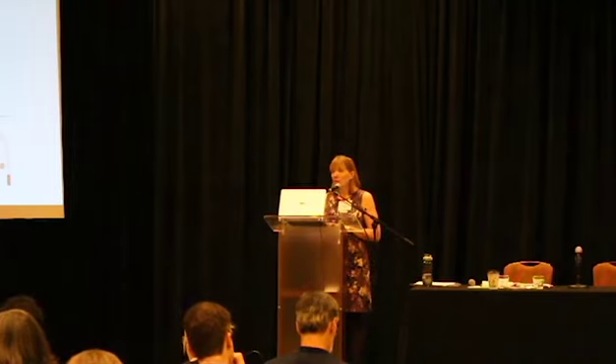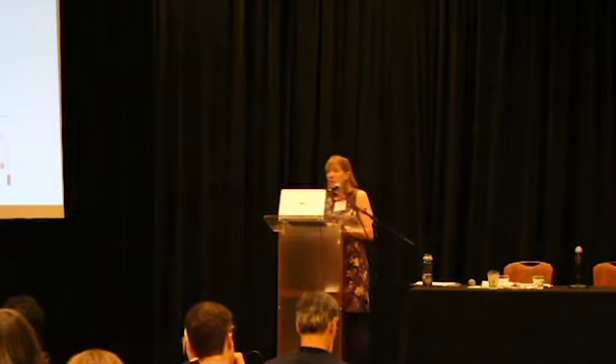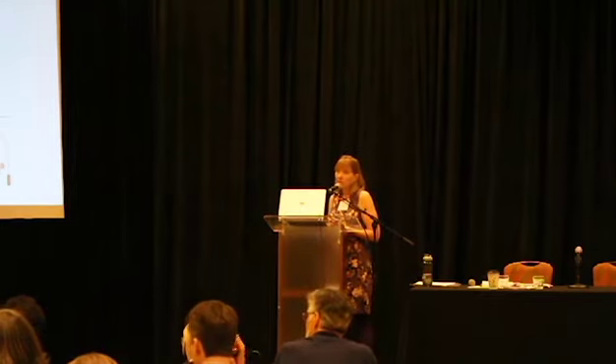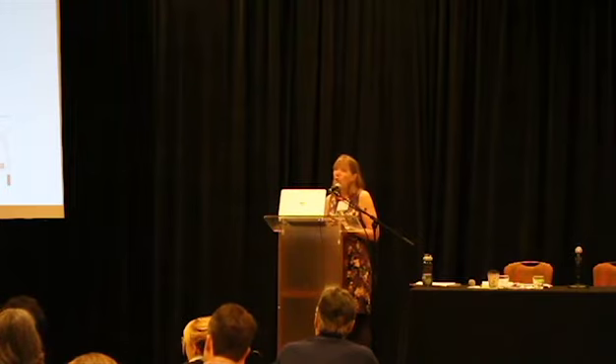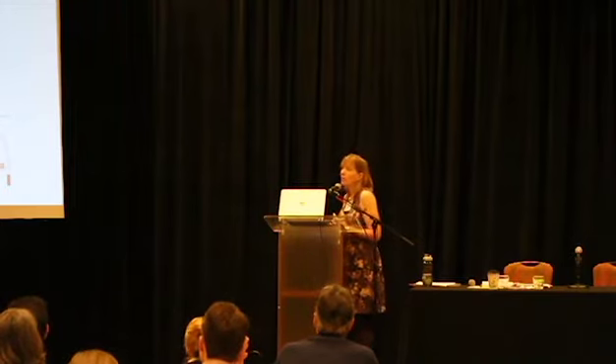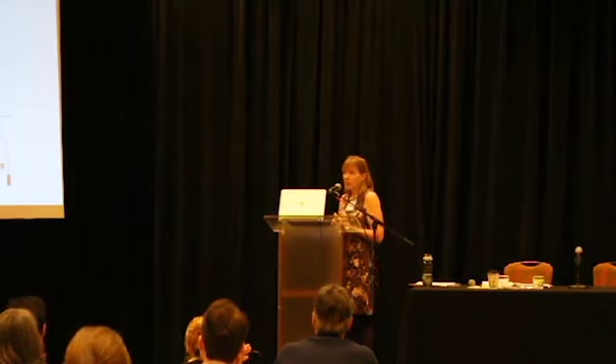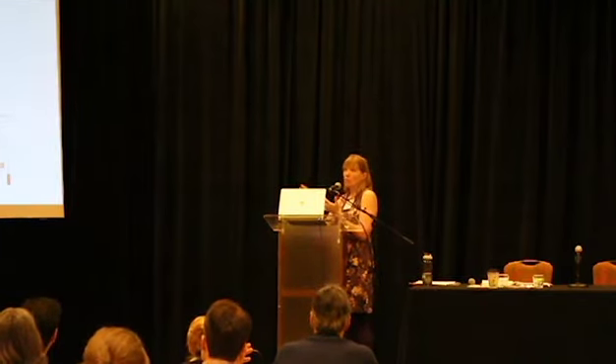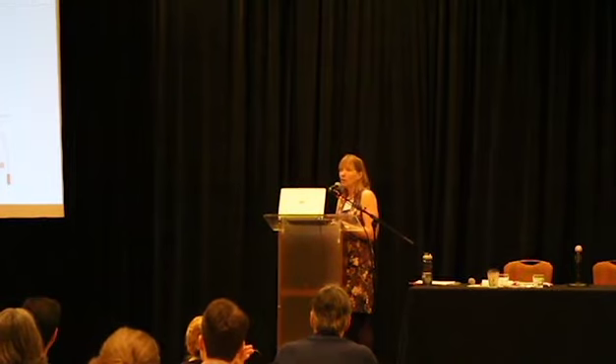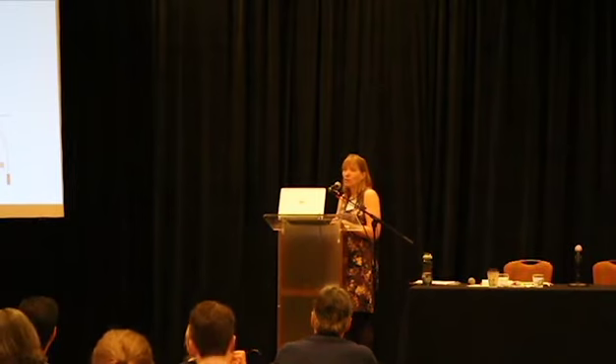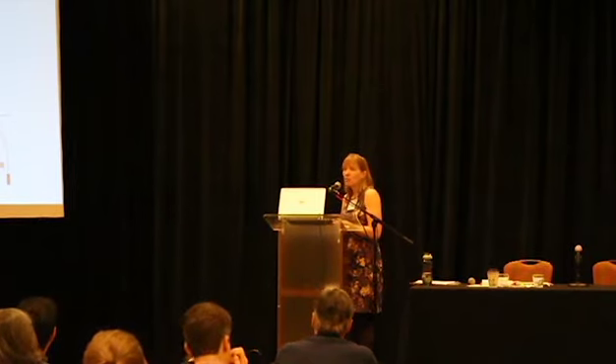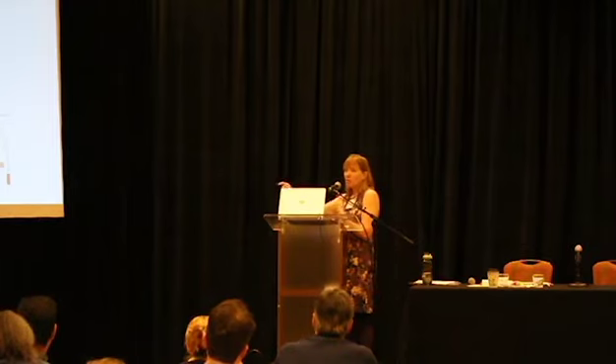Okay, and one more quick question. Earlier on, you showed some slides of some test results where they had individual tank readings and individual pipe readings, and you said they weren't supposed to test them individually, so I'm assuming... No, you are supposed to test them individually. They didn't have enough readings in those cases. So in an impressed current system, you need 3 readings per structure. So 3 readings on the tank, 3 readings on the piping, 3 readings on everything is just kind of a good rule of thumb. For a sacrificial system, piping is generally tested at both ends of the pipe run,